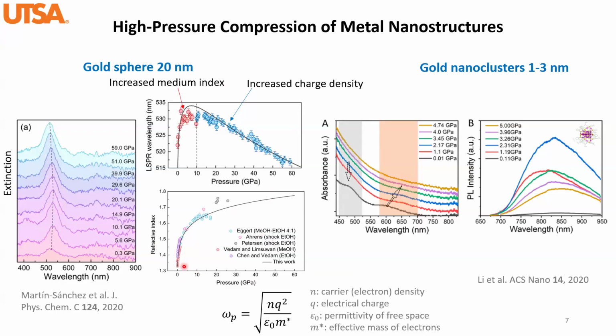Yes, if we can change, let's say, the pressurizing medium to something that is not going to have such a sensitive effect as a function of pressure, that would be really of great help. Okay. Because I seem to remember there was some proposal for a liquid-liquid transition in methanol, ethanol, water around 4 GPa. And that sort of corresponds to the change of that feature you see.